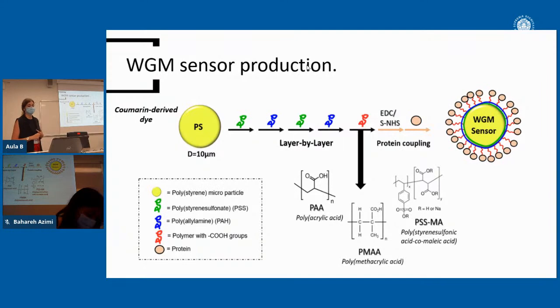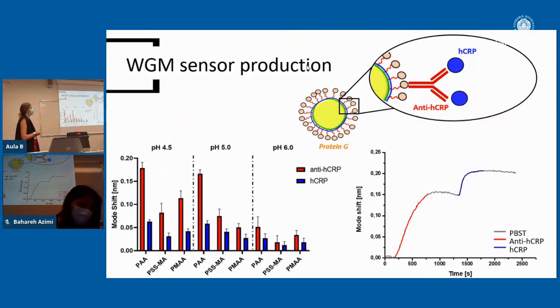EDC-NHS activation procedure. So in order to do this, we coupled protein G, which is a really famous protein used in several biosensors and also in SPR, to immobilize antibodies with the binding sites oriented to the medium on surfaces. So what we did was to couple the protein G on the different polymers and to check the binding of the antibody to the sensor and the binding of the corresponding antigen.